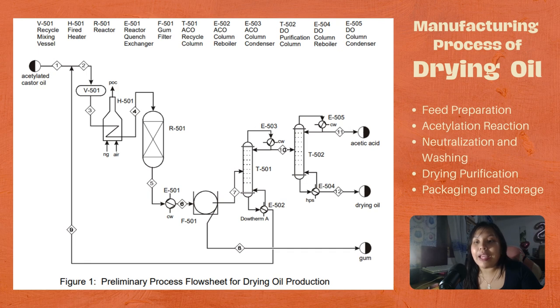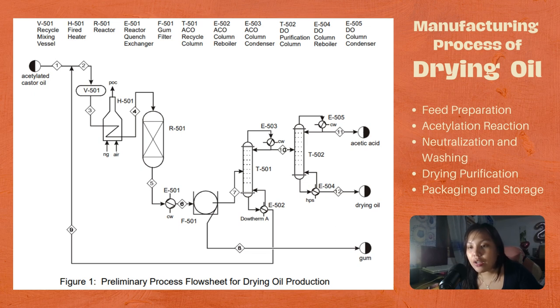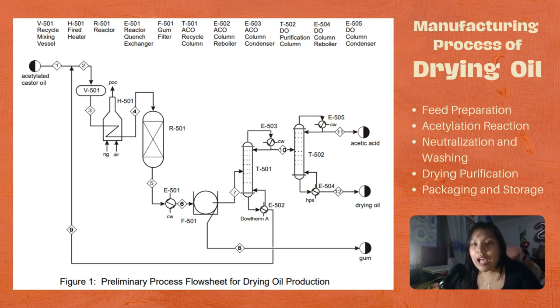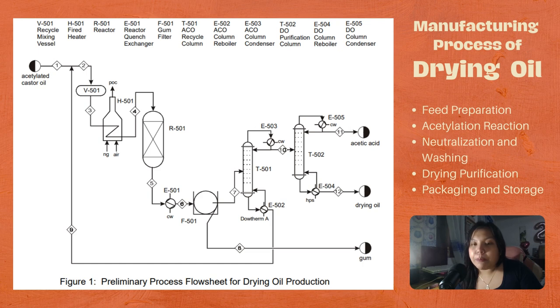After filtration, the oil undergoes distillation in T-501 with pressure determined by limiting the bottom column temperature to 300°C. The distillate contents proceed to a heat exchanger, developing a condensed saturated liquid that is transferred to another heat exchanger, producing saturated vapor at a column pressure determined by the temperature constraint at the bottom of the column, where it is recycled. The Dowtherm enters at 380°C and leaves at 360°C; it must be reheated to 380°C in the fired heater. The Dowtherm temperature must be above the temperature of the vaporizing stream.